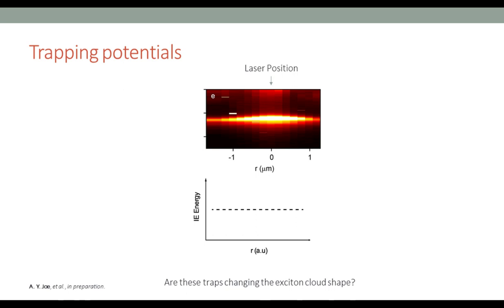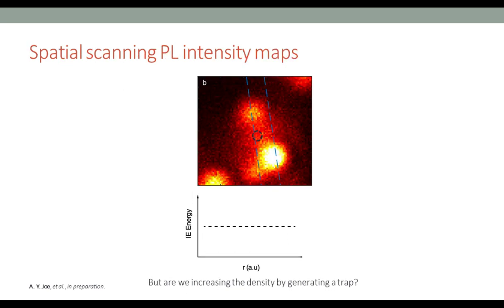And so now we can look at how the actual exciton cloud shape changes. What does it actually look like when you scan across our entire sample? With the same kind of idea, we excite in the center in this black circle region, and then we collect all across our sample, just the counts that we're seeing. What you can see is that there are already some inhomogeneous regions on our sample. When we make an anti-trap, we can drive the excitons away from our excitation spot, but we can't actually drive them away from these brighter spots that are occurring on our sample.